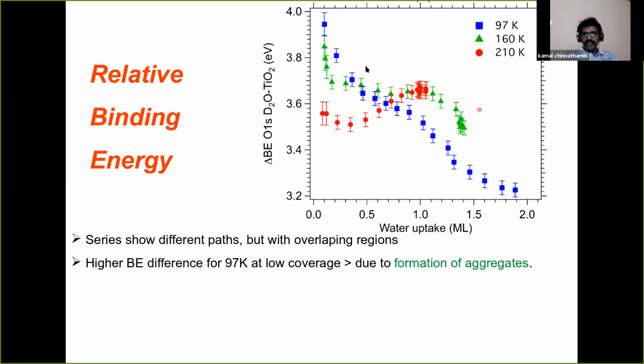If you look at the 160 Kelvin, it also starts from high values and then comes down, and then almost saturates, and at one monolayer it reaches certain values, around 3.7 or something like that, and then again decreases. The decrease after a monolayer is very well expected, because once one layer is formed and you pour water on top of the first layer, more network is forming. So it is again expected that the binding energy values will decrease.